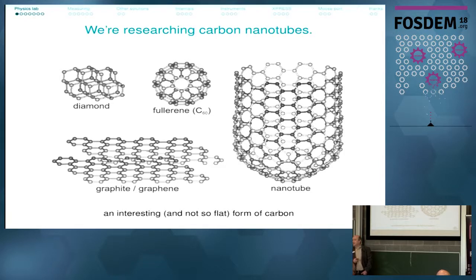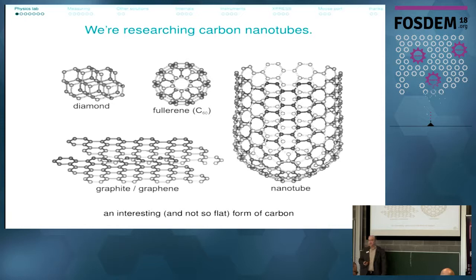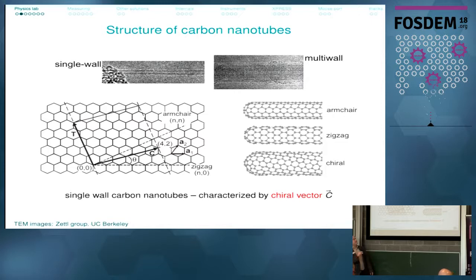There are many different forms of carbon. You can have diamond, with a three-dimensional lattice of carbon atoms. You can have fullerenes. You can have graphite or graphene with layer structures. And you can have carbon nanotubes, where you have basically one of these graphene sheets wrapped up into a tube — really one big macromolecule. You can have multi-walled ones with many shells inside each other, and single-walled nanotubes. These are transmission electron microscope images, and you can describe them with different structures — essentially this carbon sheet is wrapped up and glued together in different ways.